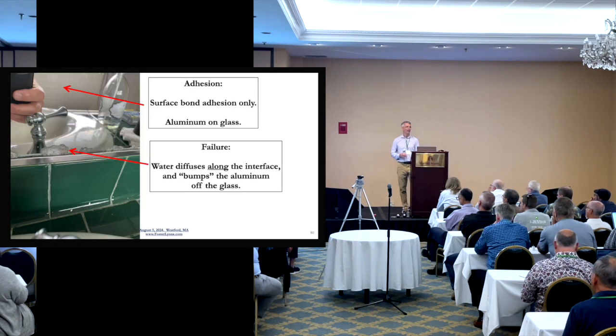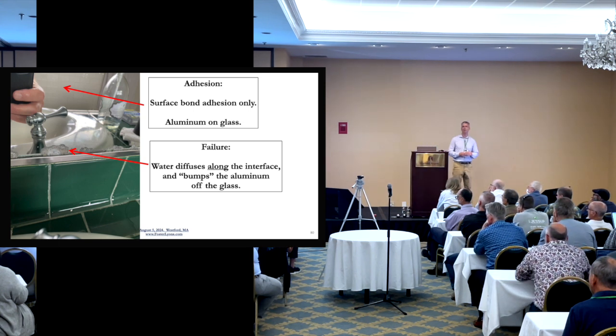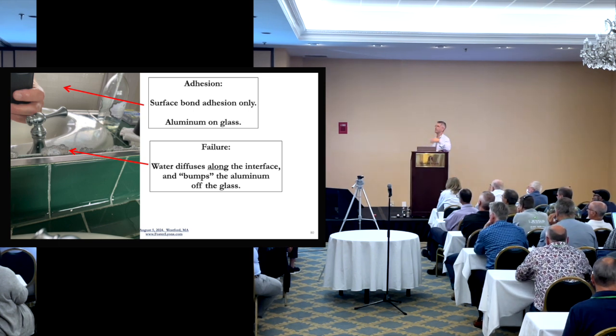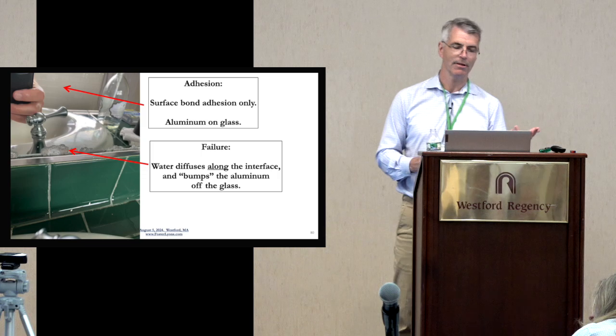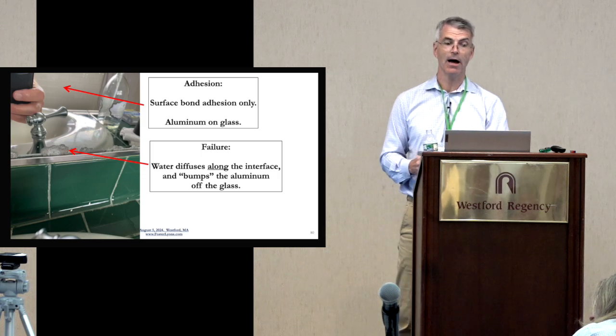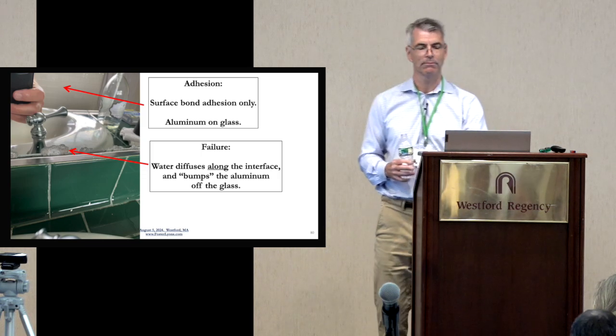they work. All right? Mirrors, you've probably all seen this at some point on mirrors, at the bottom, if you get water drops down there, all of a sudden the glass separates from the aluminum, and that's just water diffusion along the interface. So you're losing those surface energy bonds. Literally, the water molecules are just bumping the limited number of crappy surface energy bonds that existed there, right? And this is very common, by the way, in construction failures. Water causes a lot of trouble for construction, and that's it.